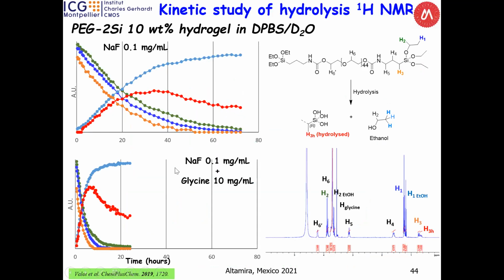I don't know if I can talk about NMR. I think we don't have time, but how we can follow the gelation time, the hydrolysis, by NMR. By NMR, I would like to explain one point. You can follow the diminution of this signal, for instance proton 2 here. We can see clearly that after several hours it decreases, and at the same time you release some alcohol, ethanol. So the formation of this methyl group here in blue, and you can see the increasing of this one. So this one is with 0.1 milligrams.